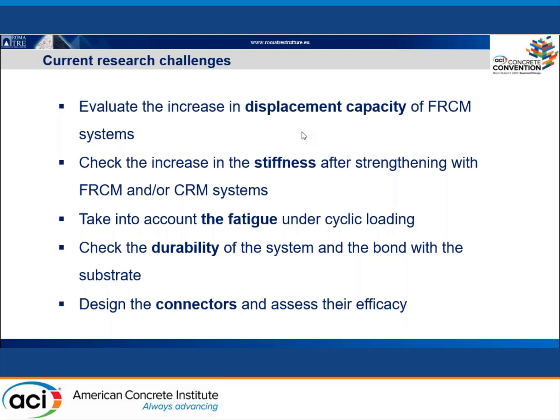Yeah, thank you. This is a very important point. I completely agree with you, because especially in systems like carbon and PBO that experience sliding within the matrix when subjected to bond tests, a coating or impregnation of the fabric or surface treatment of the fabric is very important. I think that most producers are taking care of this aspect, because this coating is very important to improve the bond, and also maybe to improve durability of these systems, because with the coating you also avoid the exposure of the fibers to the external agents. So this is a very important topic, especially I would say for carbon and PBO systems, maybe less for glass and basalt systems, where the bond within the matrix is usually enough.